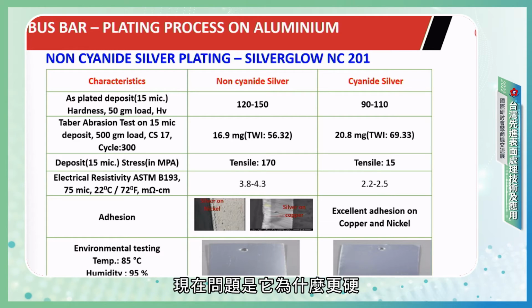Now the question could be asked, why is it harder? Basically, the reason is we have seen that the coating texture has fine grains, even finer than cyanide. So with a smaller crystallized structure, we get a more compact grain structure, which results in higher hardness.